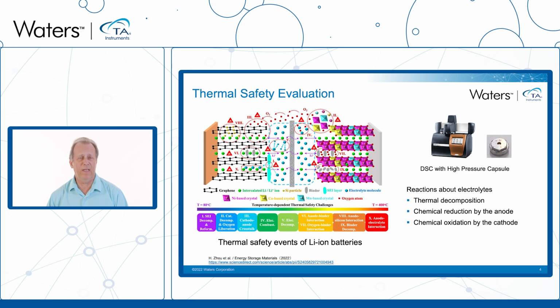So on this slide here, on the left-hand side, I have a schematic of a typical lithium-ion battery. Moving from left to right across this image here, we start off with the anode, which is basically a copper film, which has been coated with a graphite material, graphite slurry, which contains other chemicals in it, such as a polymer binder and some conducting additives added to it. We then come to the electrolyte, which is typically a lithium salt that's been dissolved in some organic solvents. There's typically a polymer separator, which is used to electrically separate the anode from the cathode. The separator can allow lithium ions to pass through it, but it will not allow electrons to pass through it, thereby providing the electrical separation that's necessary.